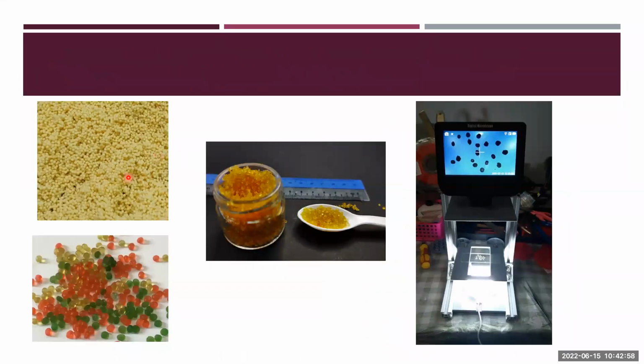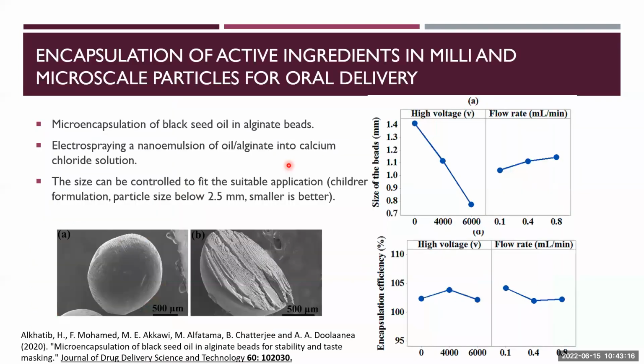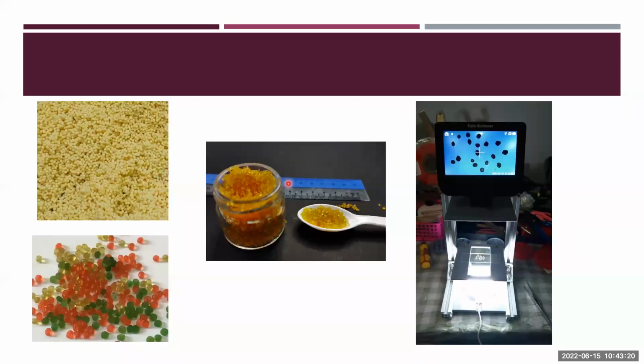This is the particles that we produce. And actually, this is the same particles that we scale up in KOP. We built a complete production line for these particles. But in the production line, we have not used the voltage. We just use the normal spray. But it's actually ready to use the high voltage, but the size was suitable for our application without the high voltage. We just didn't use it.